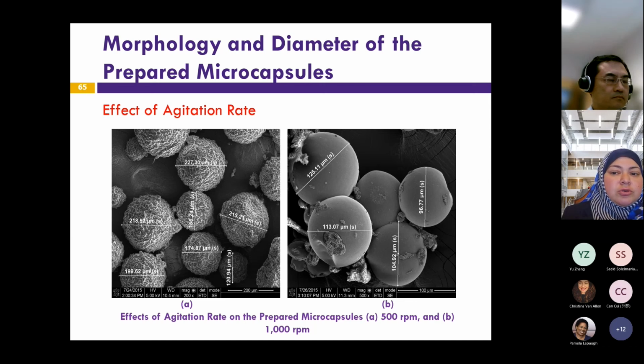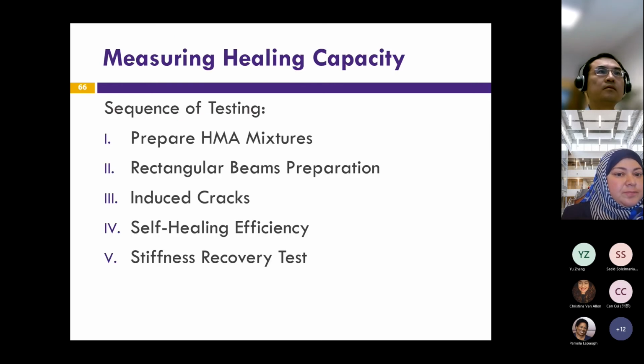Also, we use double walls to make sure that the capsules are strong enough to withstand the mixing and placing construction processes of asphalt mixes. Okay, so in terms of testing, we prepared the HMA mixtures, placed them into rectangular beams, tested the beams in 3-point bending to induce cracks, and then left them to heal, and then looked for the healing efficiency and the stiffness recovery.